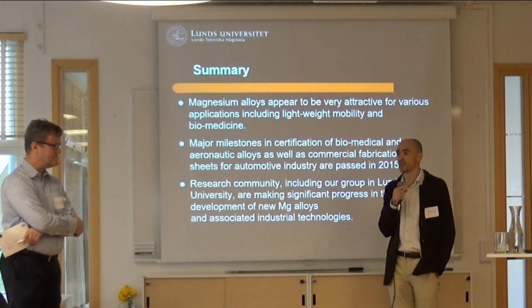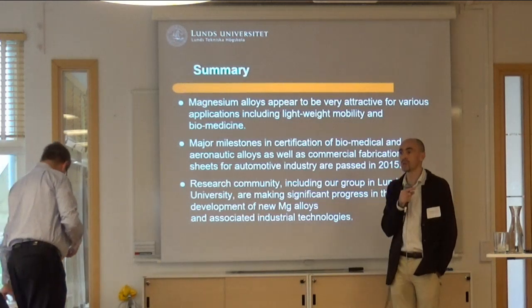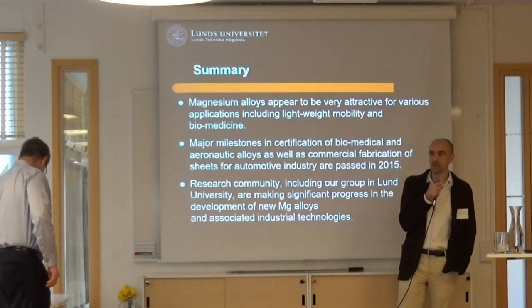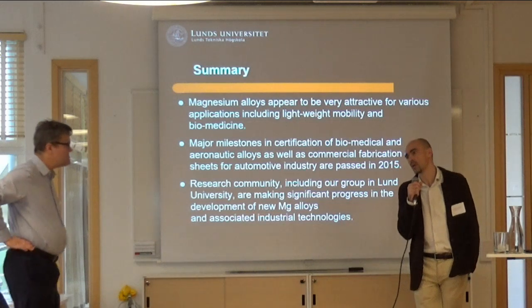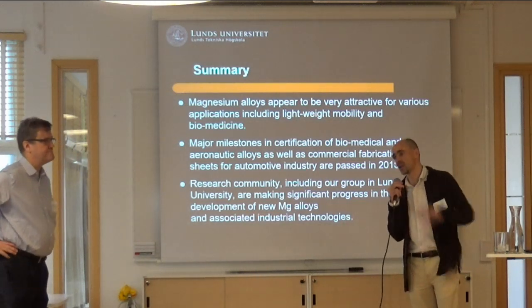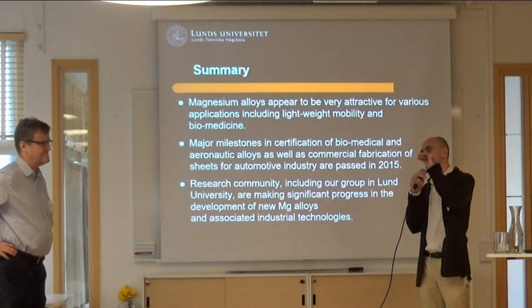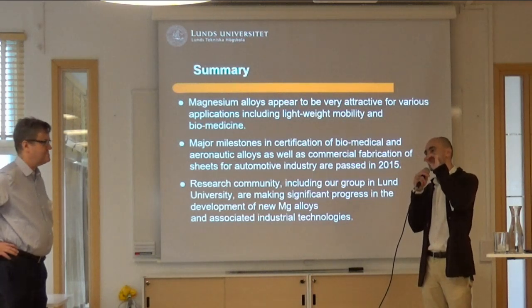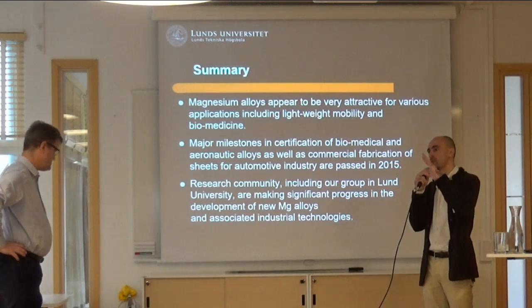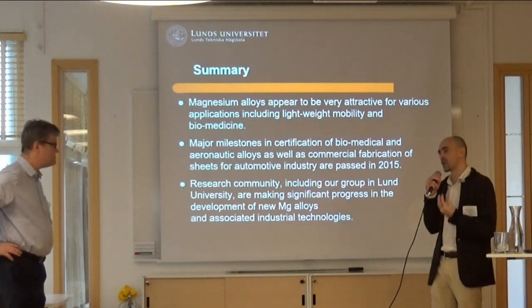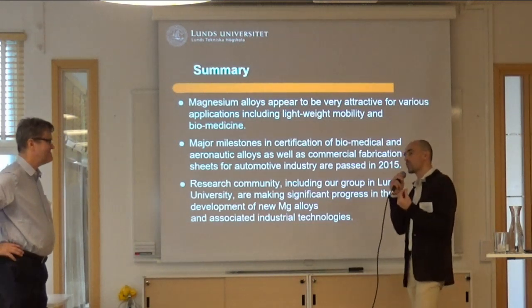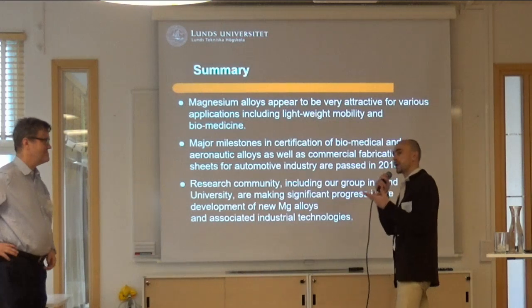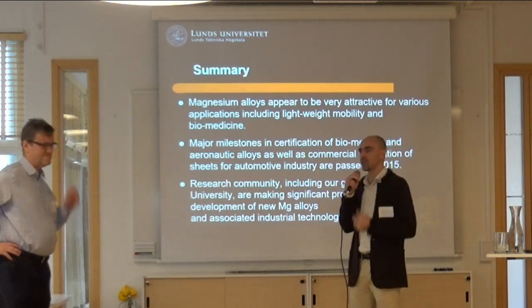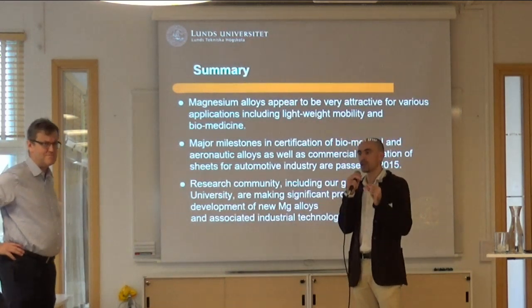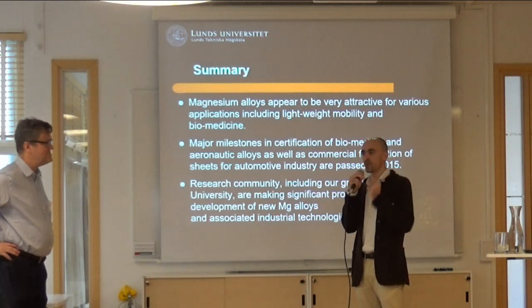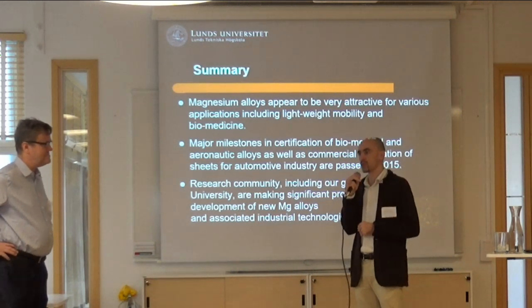Then there is plasma oxidation, which is these days quite commonly used in magnesium chassis for electronics. So there are a couple of technologies that allow this. You produce a very thick oxide on the surface, which does not oxidize in a way similar to aluminum. Magnesium oxide, MgO, is soluble in water, unlike aluminum oxide, so normally it doesn't stay there. But with plasma oxidation, you make it very dense and non-soluble. Then it works excellently as oxide protection.